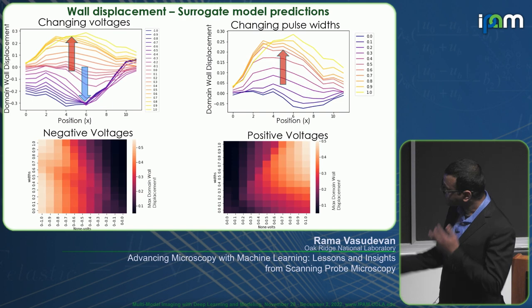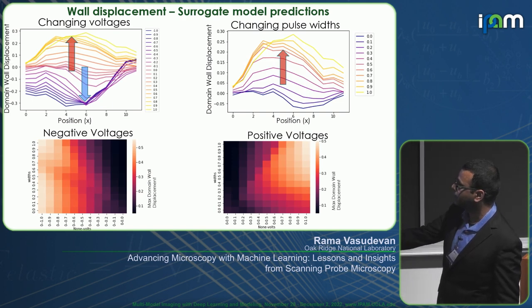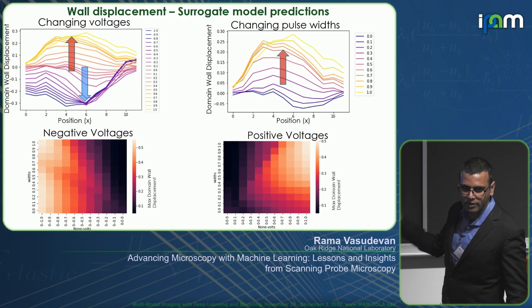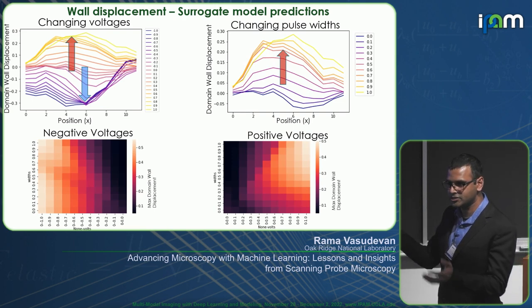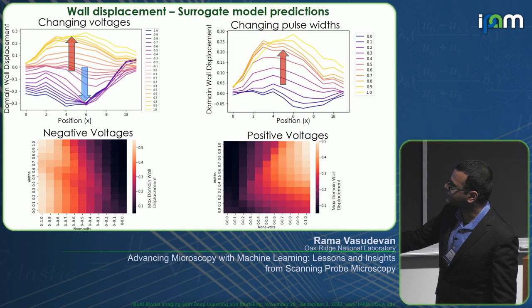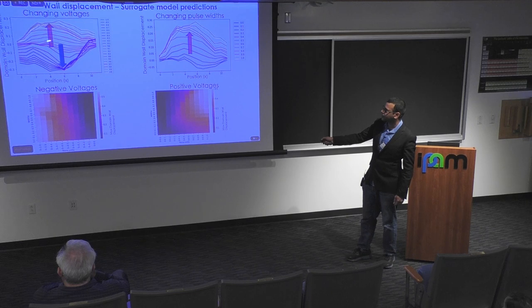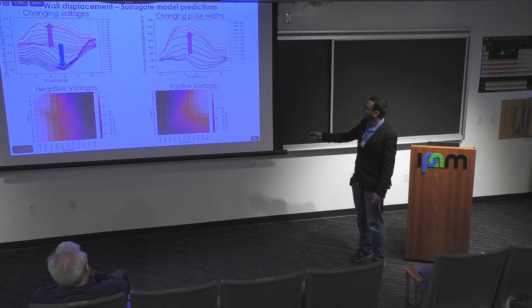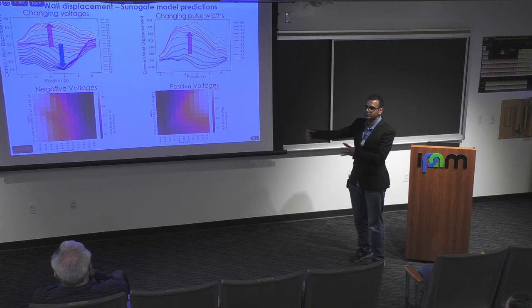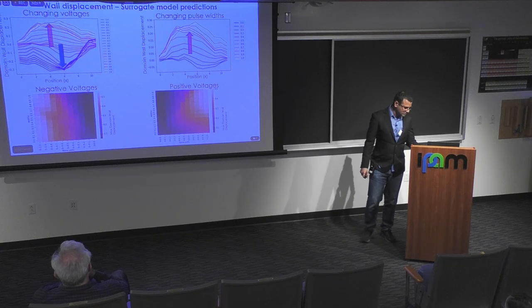And this is what you see. This is a trained surrogate model. This is a trained neural net. After we ingest all that data and do some training on it, we can see that as we increase the voltage, the wall actually displaces as we'd expect. Increasing voltage pulses result in increasing displacements, and increasing voltage pulses on the negative side result in increasing negative displacements, exactly as you would expect. And similarly, if you just look at changing the pulse width, increasing the pulse width results in the wall moving further, which is exactly as you would expect.